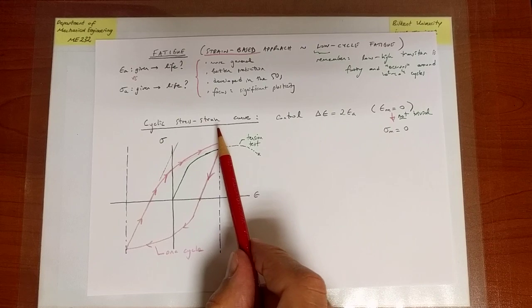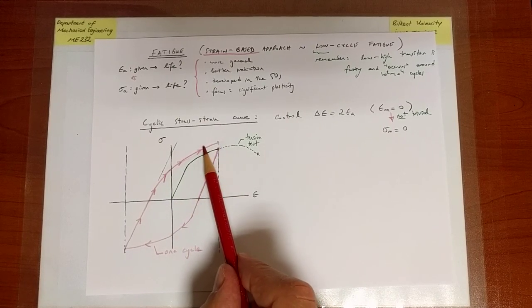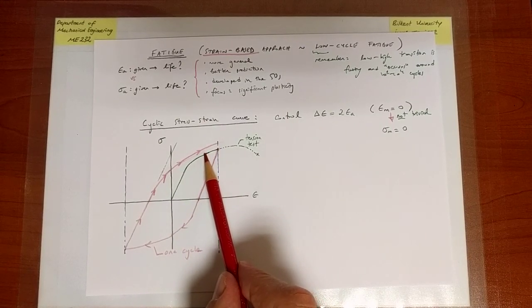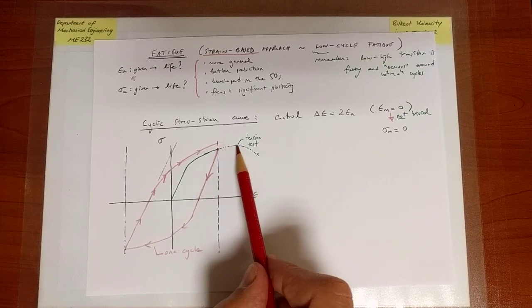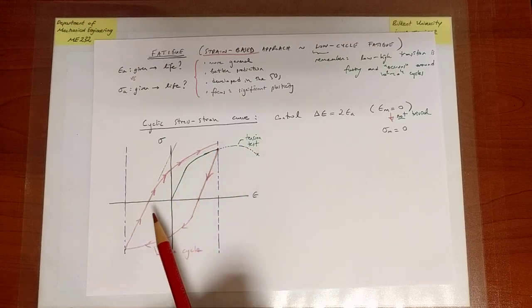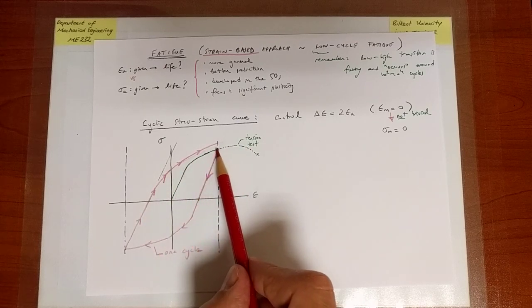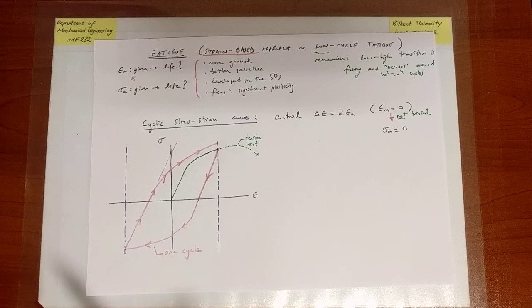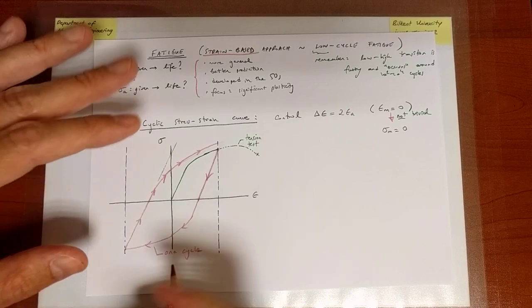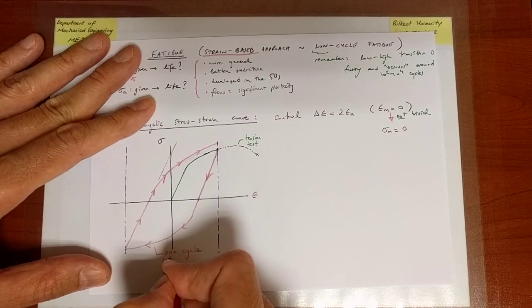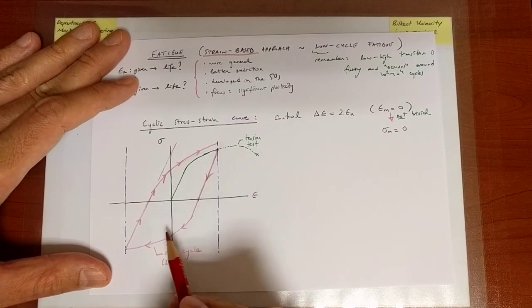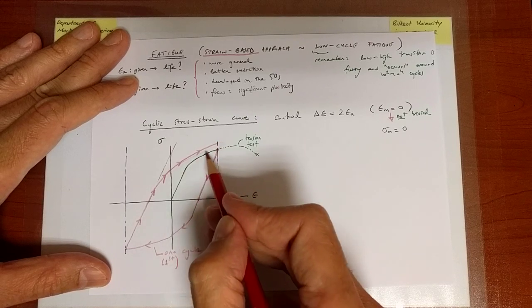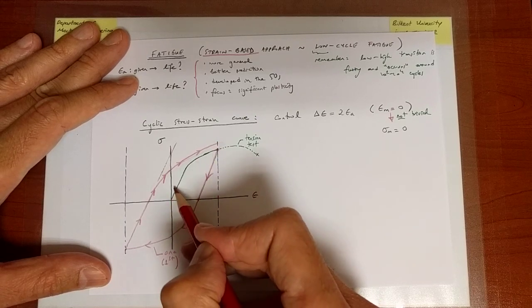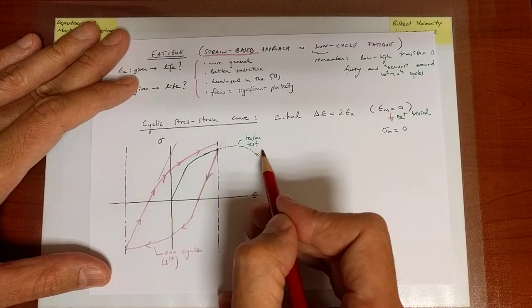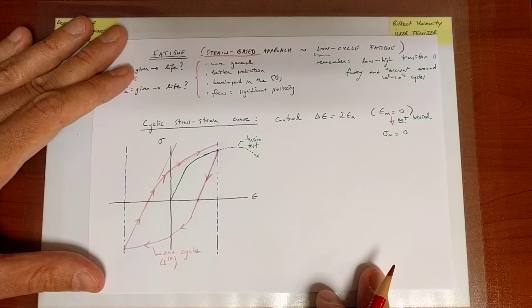Now, when I completed that cycle, notice that we did not end up on the same curve that we started from when we were starting the test, when we were approaching the start point of the one full cycle. So this one cycle, in fact, is the first cycle. The way it ended up is significantly different than the starting stress-strain behavior of the uniaxial tension test curve.